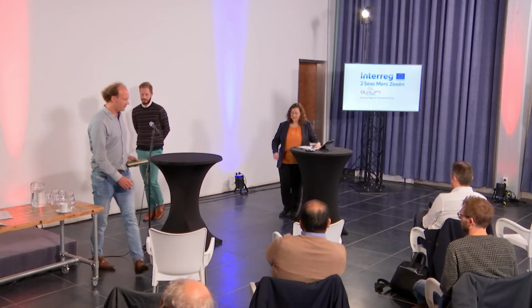Thank you, Franz. Maybe I'm not sure if this is related, but there is a question: how do we include damage in the reliability assessment? So damage has been included in some modeling. It was done while the recording of the presentation was taking place, so results were not there yet. How it is included is that, in collaboration with Bureau Veritas, we came up with this approach. If damage nucleates at the free interface of the joint, it's visible quite early, so it's not that severe. The most severe case that we can consider is that the damage nucleates on the interface on the side that is hidden from the naked eye, where it's connected to the foam part.